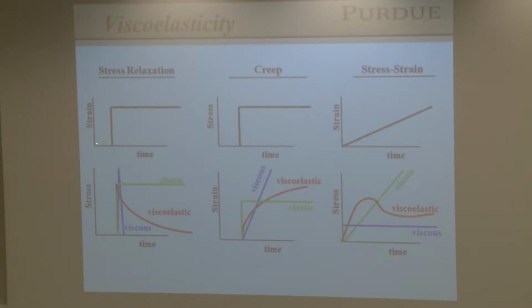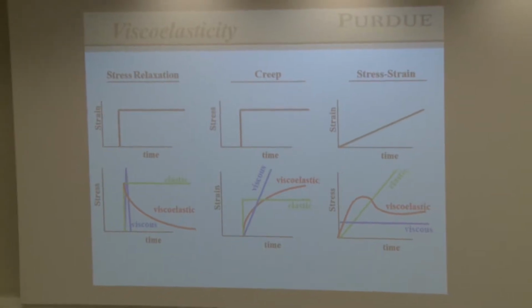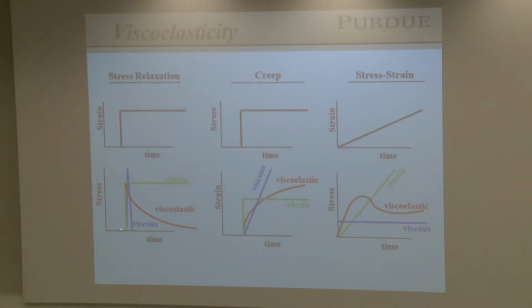In the first figure up here, we're going to take the strain, and we're going to put a step change in strain on a material. If we had an elastic material it would respond like this green line. It would also respond with a step change response in the stress. If we had a viscous material, during this region the strain rate is 0. Over here the strain rate is 0. And the only place the strain rate is changing is during the step change, and it's changing infinitely fast. And so over here a viscous material would have an enormous spike right here when the step change is applied. A viscoelastic material doesn't look like a viscous material or an elastic material.